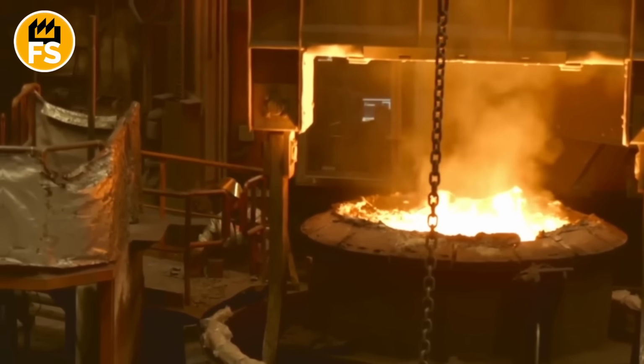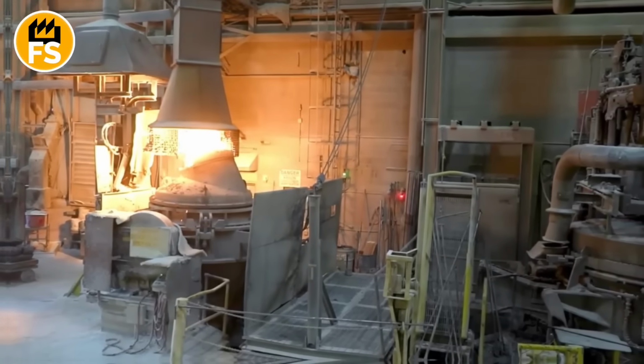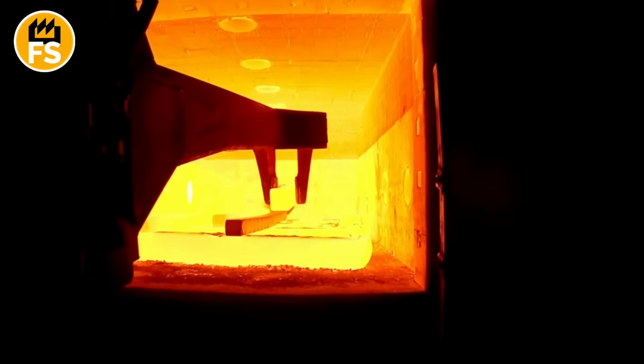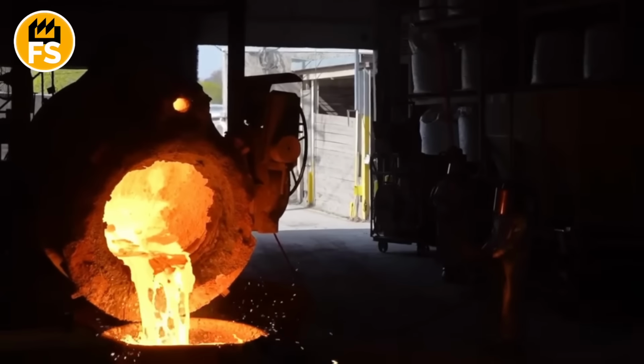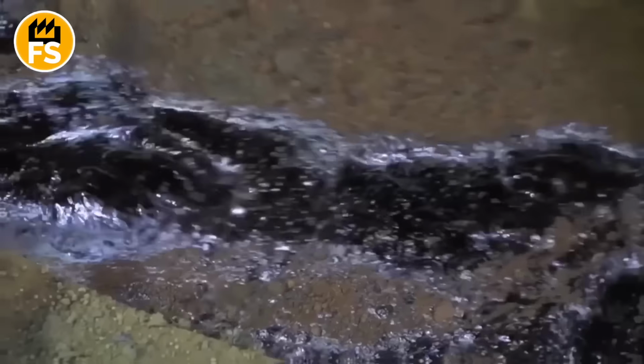The molten lead, which is extremely heavy, settles to the bottom of the furnace. On top, a layer of slag forms. That's the melted impurities. Molten lead is periodically drained from the furnace, but this isn't pure lead yet. It contains impurities of other metals, such as copper, silver, gold, bismuth, and nickel. That's why lead goes through one more stage, refining. This could be heating to specific temperatures to remove impurities, or electrolytic refining, where electric current separates lead from other metals, achieving very high purity. It's at this stage that valuable byproduct metals like silver and gold, which accumulate in lead ores, are extracted.